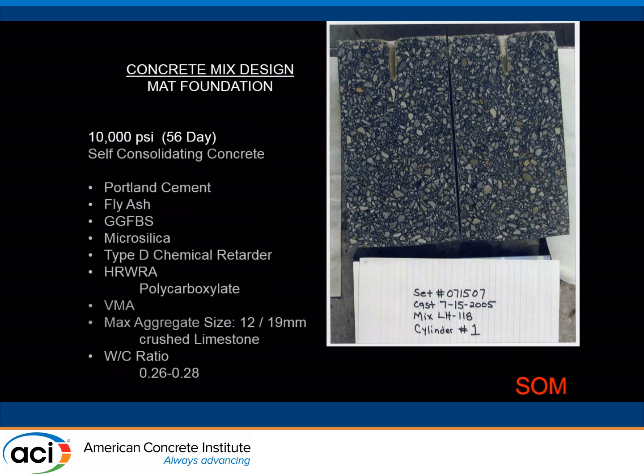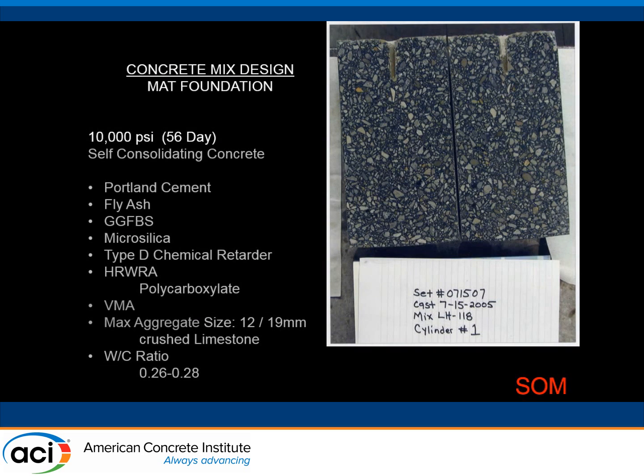Some of the stats on the concrete mix for the 10,000 psi mix: self-consolidating, as I mentioned, Portland cement, and then the usual suspects that you'll see as a recurring theme: fly ash and slag cement replacement, microsilica certainly. Here we have a type D chemical retarder, again, to try to control that differential thermal gain in the mass concrete. And then a high-range water-reducing admixture, again, coupled with a viscosity modifier to stabilize the mix and avoid segregation. Max aggregate size was bumped up a little bit. We've got a blend of a 12 and 19 millimeter crushed limestone. And water cement ratio jumps a little bit from what we saw in the outrigger zones, 0.26, 0.28, still relatively low.